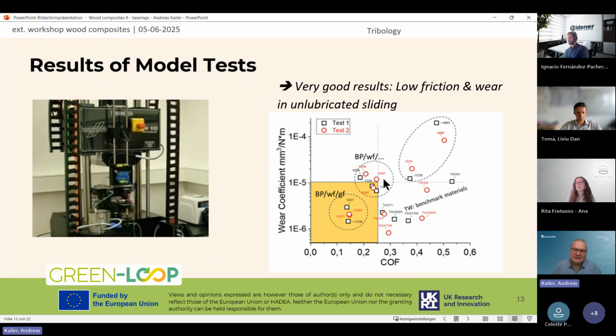And you can see in this orange field, we have directly got some materials that show very good friction behavior. So friction coefficient of these materials around 0.15, which is quite low for unlubricated friction. And we have also got wear coefficients in the range of 10 to the minus 5 to 10 to the minus 6.